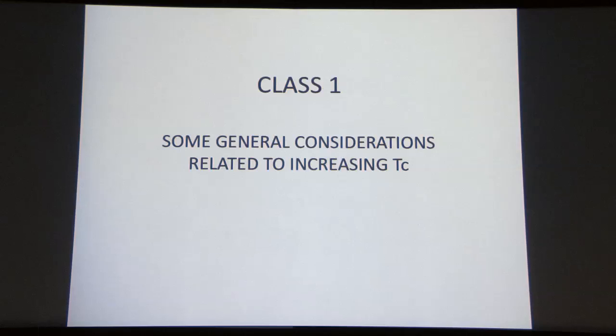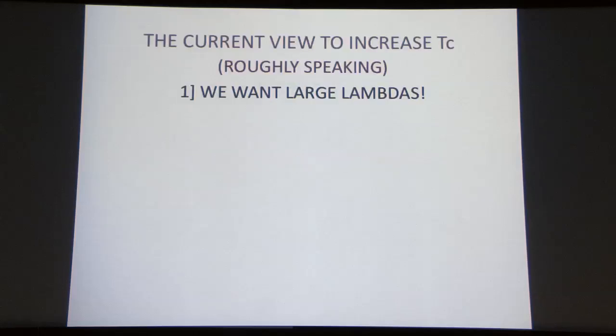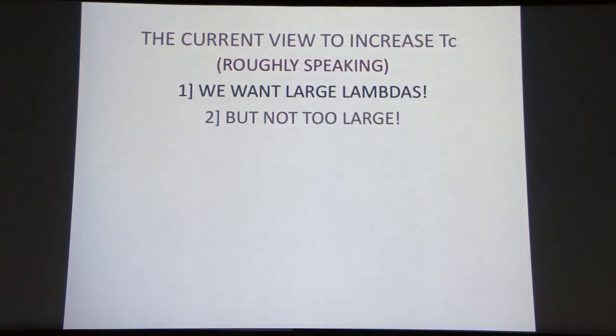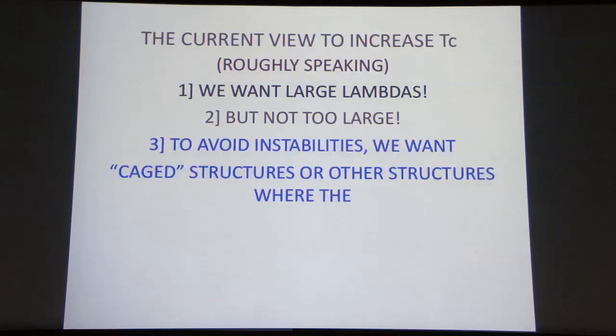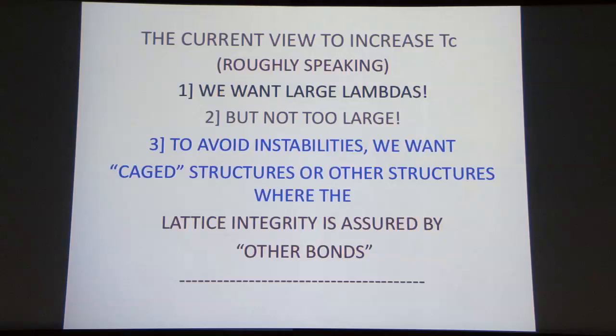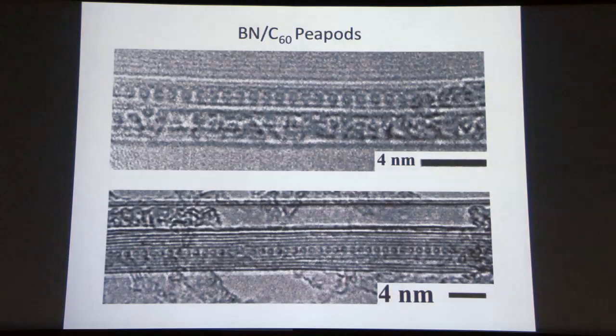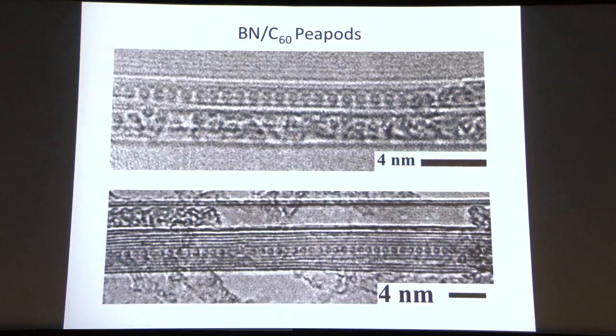So the question is, since you understand class 1, can you get the higher transition temperatures? And this will be the last subject. So we want large lambdas. We want the electrons to couple strongly to the lattice. We don't want it too large because it'll distort the lattice, go unstable, and you'll lose the effect. So we avoid instabilities by going to cage structures where the system is held together by something else. I'm going back to this, for example, these boron nitride nanotubes. We've put in the C60s, and now they're putting potassium in, and the potassium is interacting with the C60s, trying to get a higher transition temperature.